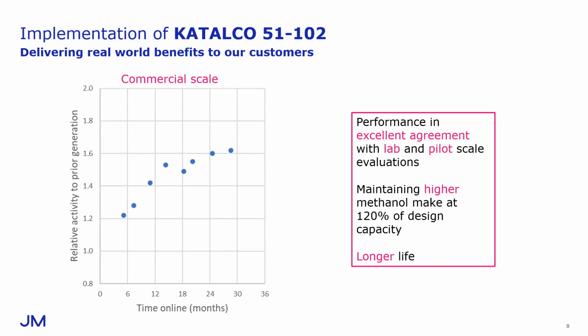Now, both catalysts deactivate with time, but because 51-102 is more stable and therefore deactivates less, there is a relative activity benefit that accrues over time. And as illustrated in this figure, this reached a factor of about 1.6 after about 2 years online. And we expect this activity advantage to continue to increase with further time on stream. And clearly this represents a huge improvement in the performance of the catalyst versus prior generation materials.